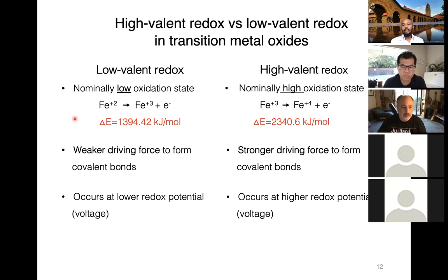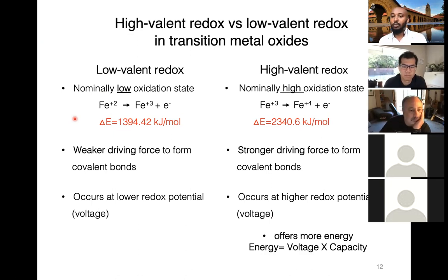And then last but not least, this high-valent redox process takes place at high voltage. Since the energy we can store in a given material is capacity times voltage, and since high-valent redox offers us high voltage, that means we can improve the energy of a given material by improving the voltage through high-valent redox. And this is why high-valent redox is relevant for improving the energy density of battery materials, because it happens at higher voltage.